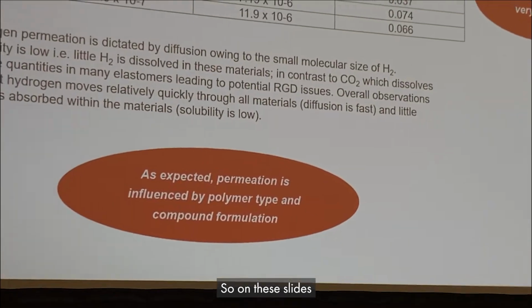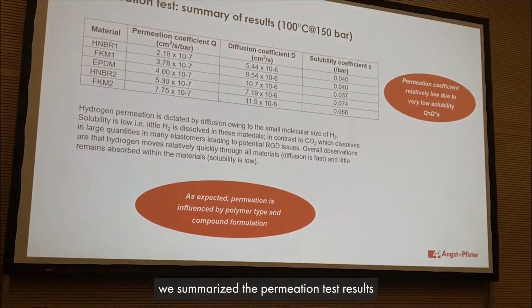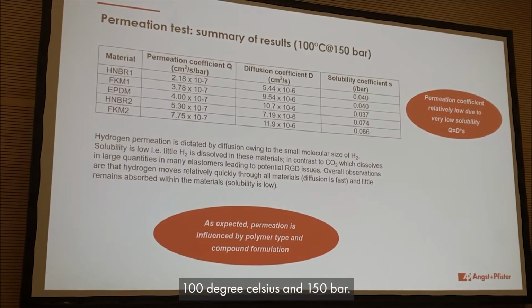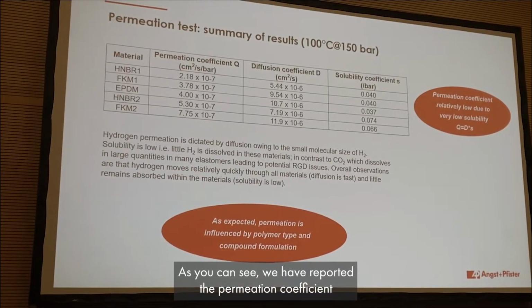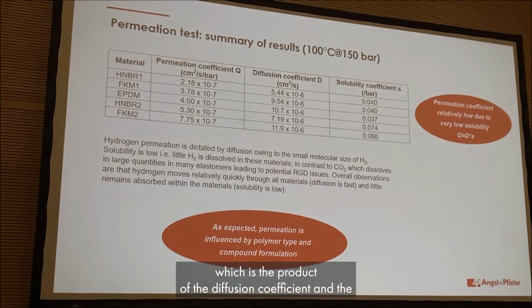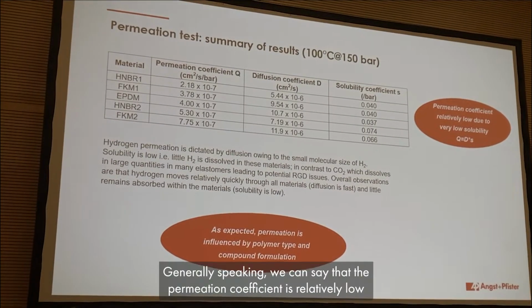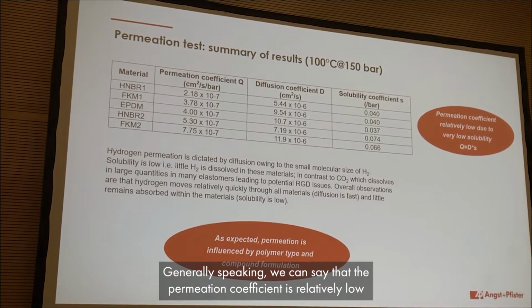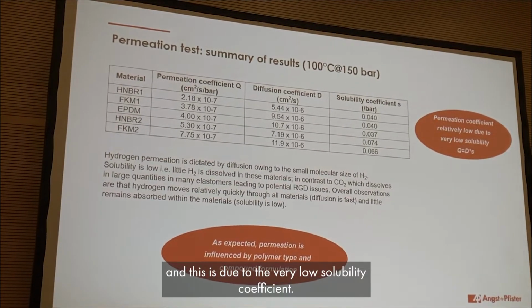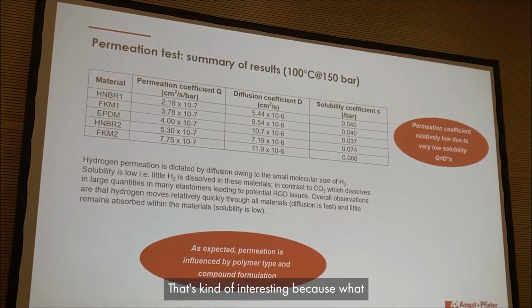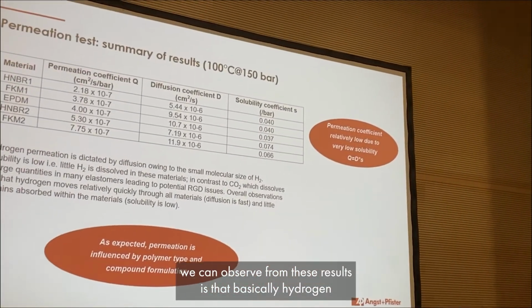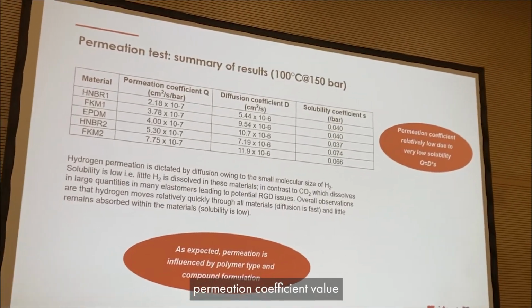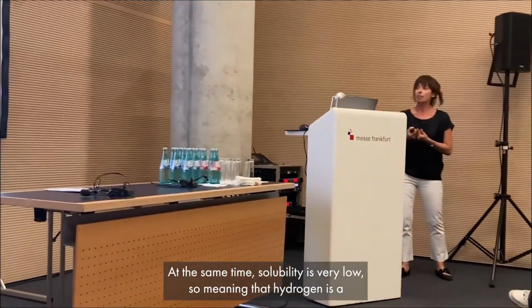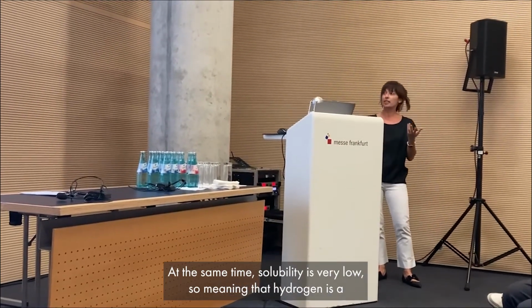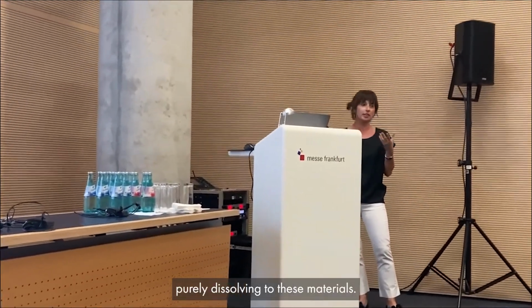So, on these slides, we summarize the permeation test results, 100 degrees C, 150 bar. As you can see, we have reported the permeation coefficient, which is the product of the diffusion coefficient and the solubility coefficient. Generally speaking, we can say that the permeation coefficient is relatively low, and this is due to the very low solubility coefficient. That's kind of interesting, because what we can observe from these results is that basically hydrogen permeation coefficient values are dictated by the diffusion due to the small molecular size of hydrogen. At the same time, solubility is very low, meaning that hydrogen is poorly dissolved into these materials.